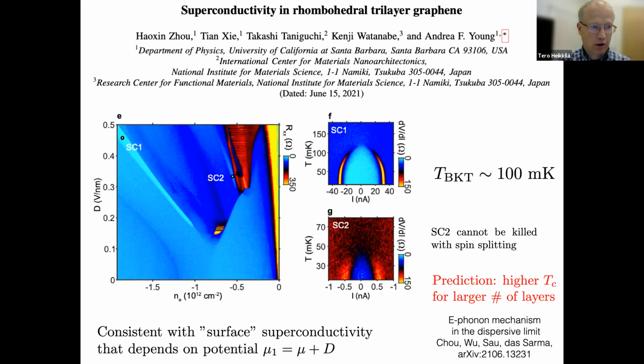The SC2 is somewhat interesting because they also studied what happens in the presence of magnetic field. This is not shown here, but what they showed was that the in-plane magnetic field does not kill superconductivity here, and so they claim that maybe it's a triplet order parameter. But basically, these lobes that you see here are consistent with the fact that we are changing only the potential of, let's say, the top surface. Once you fix the potential of the top surface, this is the equipotential line, nothing changes almost, but it only changes in this direction. So this is consistent with what I described earlier.